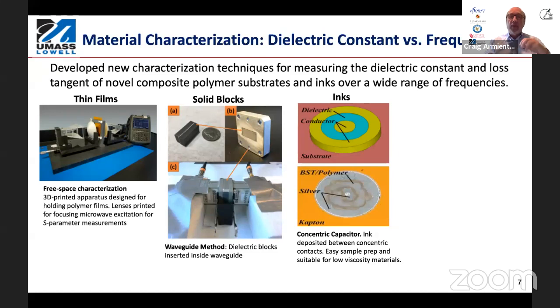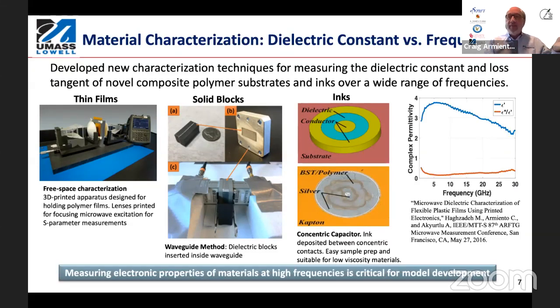So we have a process whereby we can create a printed concentric capacitor where we can probe with a ground-signal-ground probe and characterize the inks. And ultimately, we're after measurements like this, where we can measure the permittivity and the loss tangent out to 20, 30 gigahertz and so on. So that's what all this is about. These data are really critical to feed back to our models for being able to do the work we do with simulation.